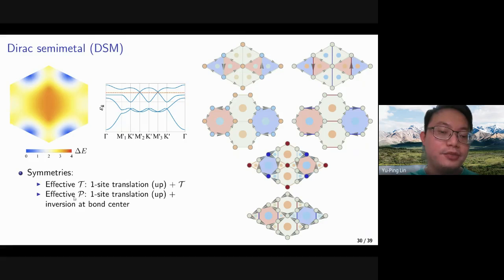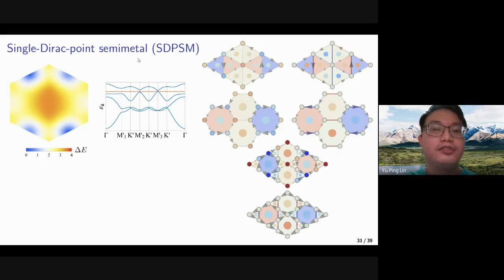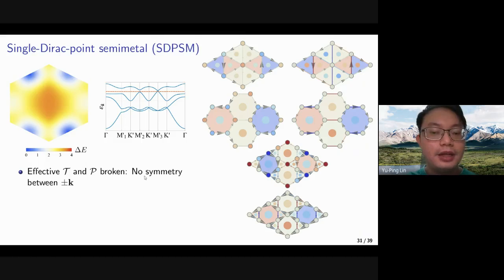Similarly, we could apply an effective inversion. That is, we again translate the lattice by one site and equivalently here, and apply an inversion with respect to the bond center to invert the current direction, and it will be invariant under this kind of transformation. So combining these two symmetries, they will protect the Dirac points at these 2 points. Meanwhile, if we don't have these symmetries, for example, if we apply a one-site translation from here to here, the site densities are different. We no longer have this kind of symmetries. So if the T and P are both broken, there is no symmetry between plus and minus K. In this case, there is no fermion doubling theorem. And we will only have one Dirac point in the Brillouin zone here. And this one will be gapped here.